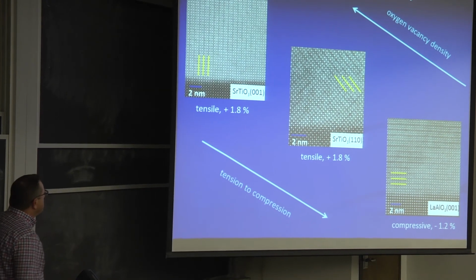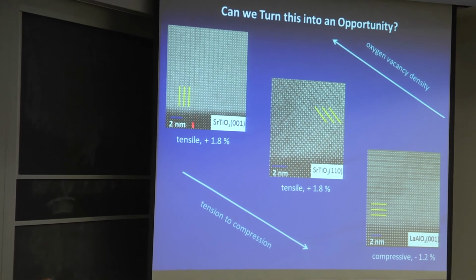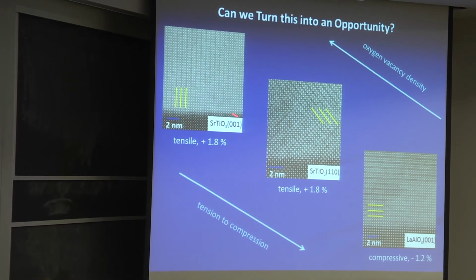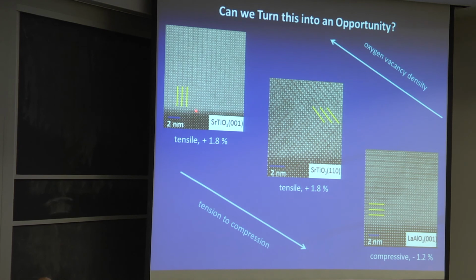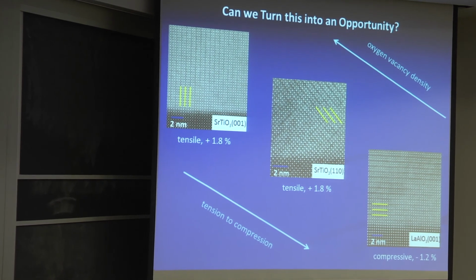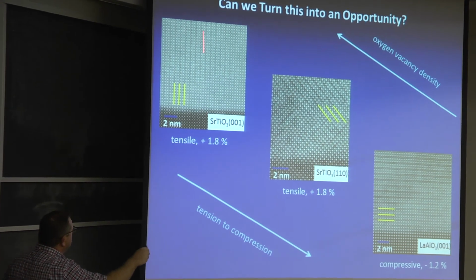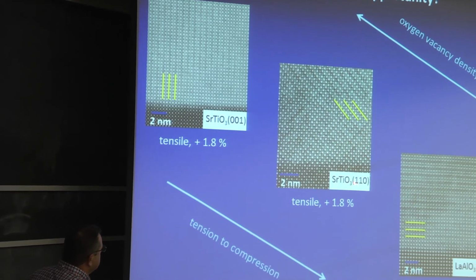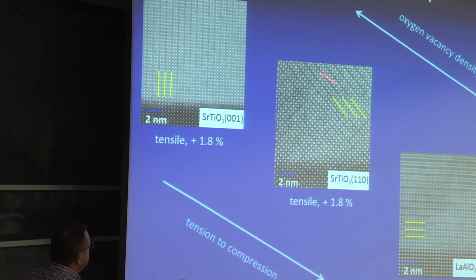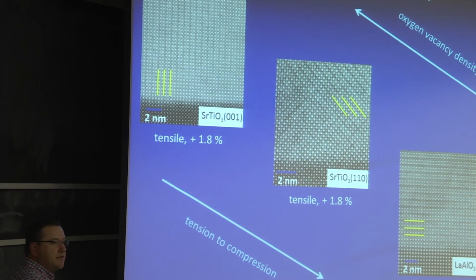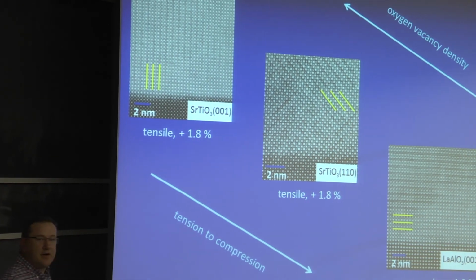And then we had a few months where we had a lot of fun with this, because once we'd seen that perpendicular image, we realized if I just mess with the substrate, I can control this. I should predict exactly what's going to happen. I know the vacancies like to run along the 001 direction. I just changed the orientation of the strontium titanate to 110. We predicted they should run at 45-degree angles. They do. And then this one, nail in the coffin, right?